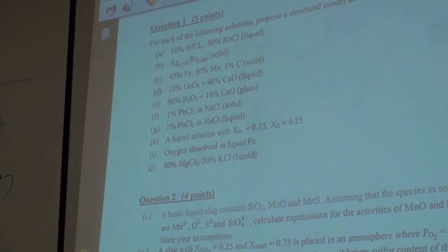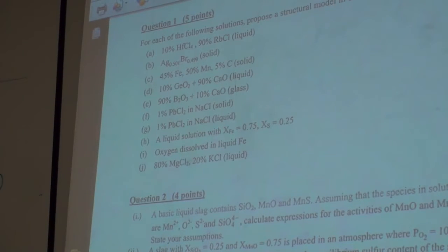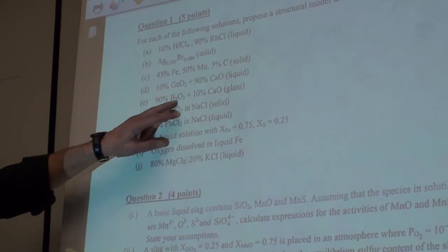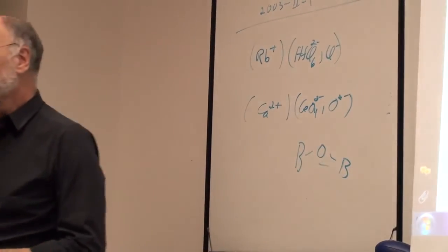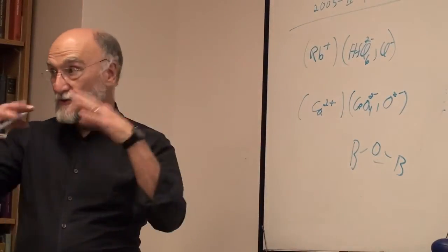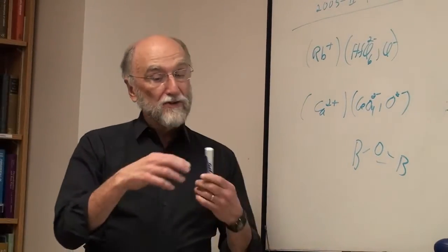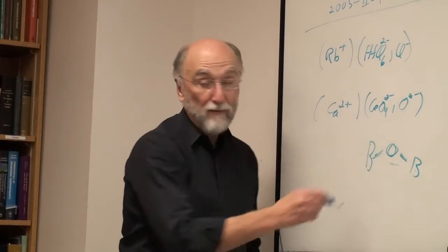It's a glass, which we consider to be more or less like a supercooled liquid. Okay, so your boron oxide, well, I'm going to talk about that later today, but it is, as you know, like a silicate network. More complex, but you do have boron, oxygen, boron bridges, just as you do in silica. So you have a borate. B2O3 pure is like SiO2. You have your silicate SiO2, you have your silicate network where every two silicons are bridged through an oxygen bridge with the covalent bonds.